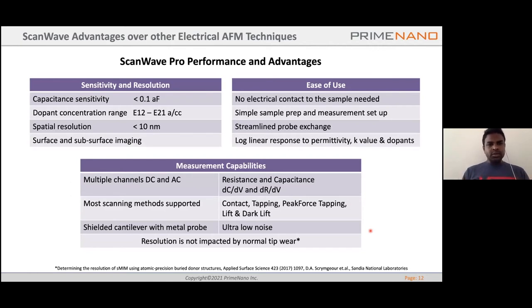Before we delve into the applications, there are a few advantages and performance parameters that I wanted to talk about. The first is the capacitance sensitivity. This is the contrast that the ScanWave Pro can see. This is less than 0.1 attofarad. That is, if there is a variation between two individual pixels, a variation of capacitance of less than 0.1 attofarad, ScanWave can look at it.